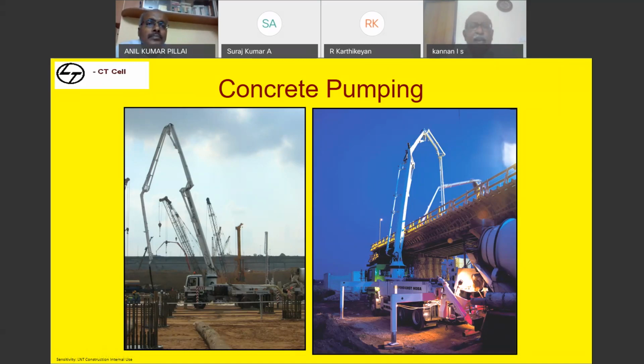When you reverse the bend, what will happen is the free fall concrete will get accumulated here, and when it is pumping, a uniform concrete will get pumped and come. So now this is a straight 90 bend. That straight 90 bend, if you are reversing it, you can get a good quality concrete, so that the concrete falls only with the 6 meter length pipeline. Nothing happens. Okay, so you can get a full hose length of concrete, because normally what we would have observed